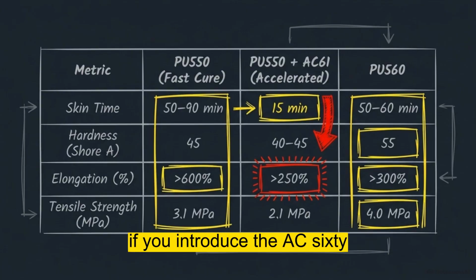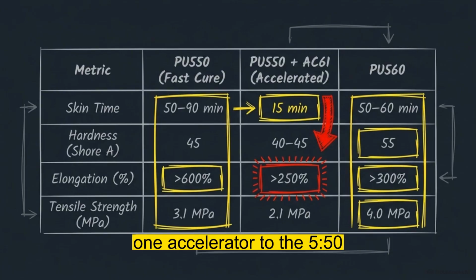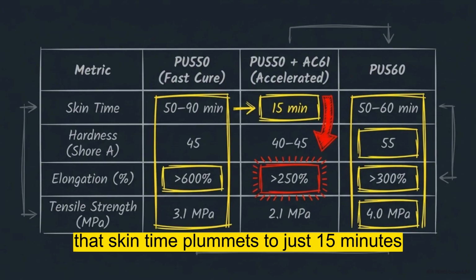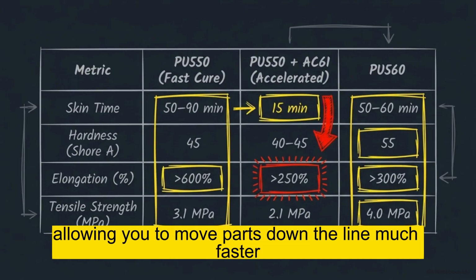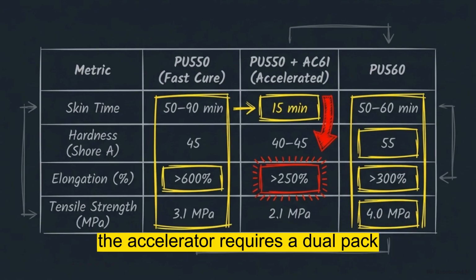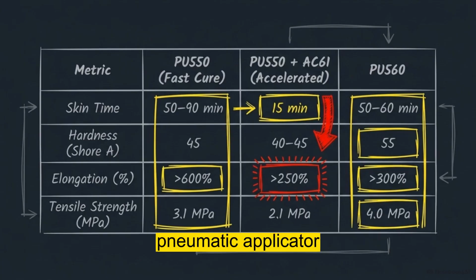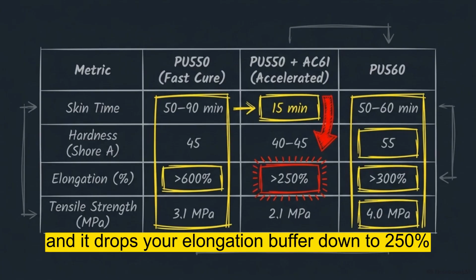If you introduce the AC61 accelerator to the 550, that skin time plummets to just 15 minutes, allowing you to move parts down the line much faster. But speed has a cost. The accelerator requires a dual-pack pneumatic applicator, and it drops your elongation buffer down to 250%.